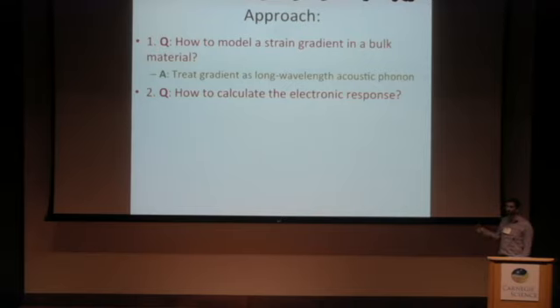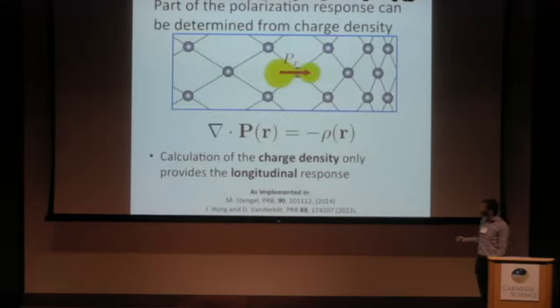The second question is, how do we calculate this polarization response that I've been referring to? So in the schematics that I showed before, they were based on looking at the induced charge density from a strain gradient perturbation, or a phonon perturbation. And the induced charge density from a phonon perturbation is something that's readily available in most DFT packages, and it's been used on previous implementations to calculate flexoelectric coefficients. Unfortunately, we see that since the charge density is given by the divergence of the polarization, it only contains information about the longitudinal components of the polarization field. And therefore, from the charge density in bulk, we can only calculate the longitudinal flexoelectric coefficients.